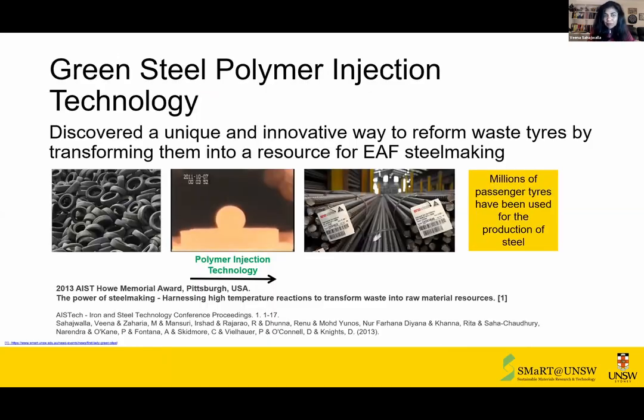Again, here an example of how that kind of reaction that you see in the middle of the screen allows us to not only carry out slag forming reactions, we've measured hydrogen that is released under these conditions, and indeed shown that the reactions that you're seeing there are taking place inside large operating furnaces.